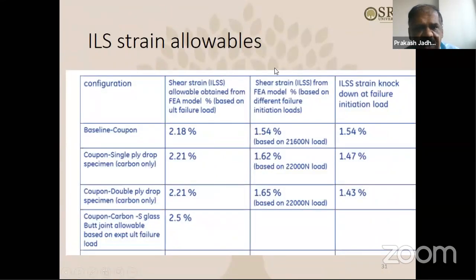And then, of course, as far as the strain allowables are concerned, how do you find the effect of this ply drop? As you can see, the baseline coupon, then single ply drop coupon, double ply drop coupons like this. So you can see the difference of these interlaminar shear strains. Okay. So this is based on the ultimate failure load, and this is based on the initiation failure load. Yeah, so this is what it shows.